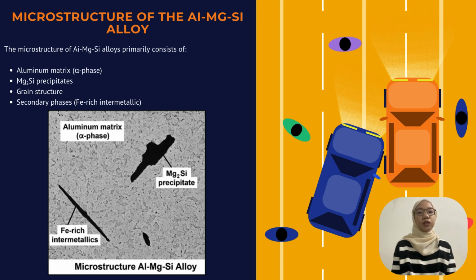Then there's the grain structure, which is carefully controlled using heat treatment and mechanical processes. This balance is important to achieve both strength and toughness. Lastly, there are secondary phases, especially those with iron. These ferrum-rich intermetallics often appear as needle-like or plate-like shapes. Although they are usually present in small amounts, we try to reduce them as much as possible because they can lower the ductility of the material. So overall, the microstructure is carefully designed to give a combination of lightness, strength, and also durability.